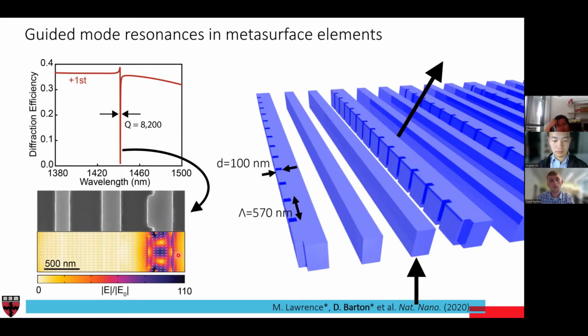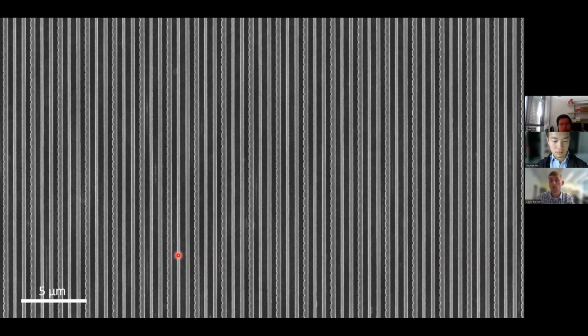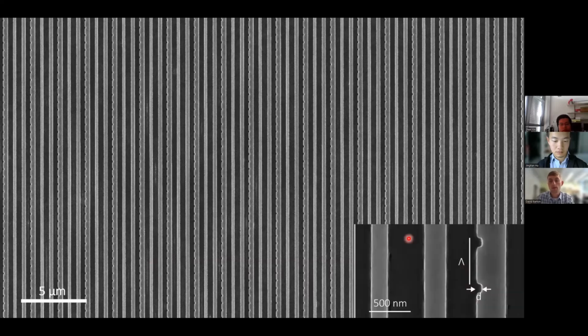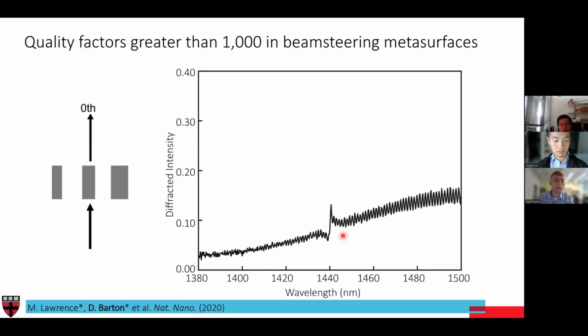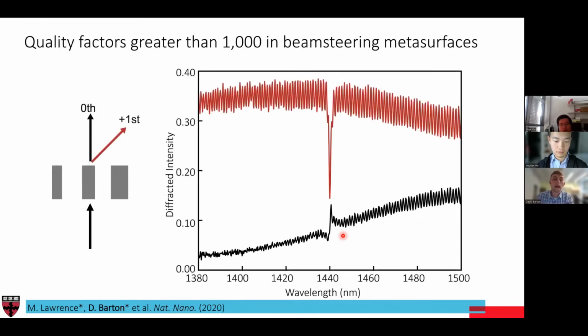And so we went about and made a large number of these samples. This is a top-down SEM of what a typical structure looks like, and a zoomed-in view here. We have a beam steering element that we've designed where we put in these grooves. If we do these experiments, we find that we can design these high Q elements in beam steering metasurfaces and in really any nanophotonic structure. We designed these to beam steer into the plus first order, so light is being diffracted to about a 45-degree angle.